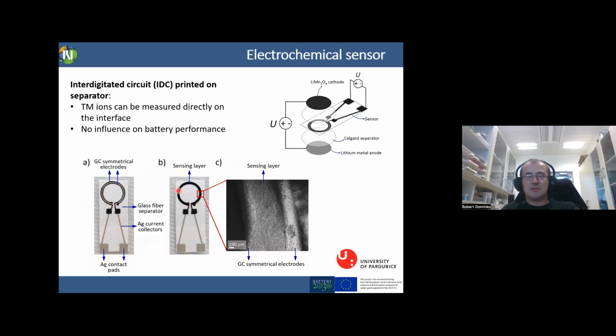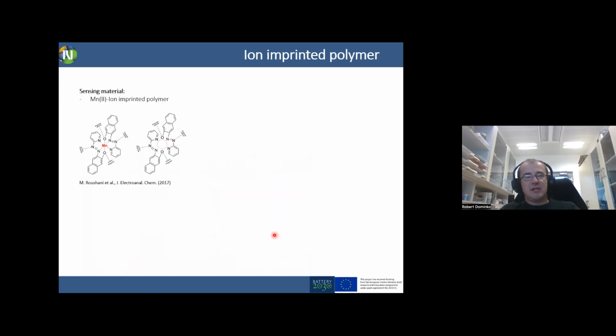And then between those two electrodes, we can put a sensing layer. You can imagine this sensing layer can be whatever you want to detect. If you want to detect dissolved manganese, then you put something that will attract, capture, and coordinate manganese, or maybe some other transition metal that can be dissolved. You can also put another layer which can detect the formation of fluorine compounds, and we are even discussing what to use to find the formation of hydrogen or some gases within the electrolyte. This sensing layer is put between the electrodes, and in our case today I will discuss